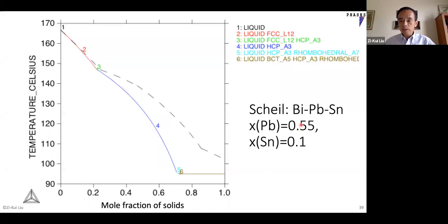This diagram shows a simple system for the solder. The dashed line is the equilibrium calculation, and the solid line is the Scheil simulation. You can see the temperature difference, about 10 degrees for the melting. So that's actually important too, the final solid temperature.